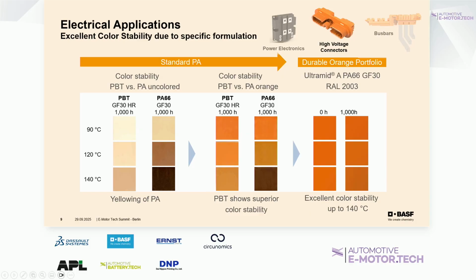And then we said, okay, let's just color it, and maybe the effect is gone, but unfortunately this was not the case. So also if you take an orange pre-colored material and age it with temperature, it still will be brown after time. So what we did, we started the development to decrease this effect as well as possible, and the result is shown here on the right side. You still see a kind of effect, so it's getting a little bit into brown, but it will still be orange after aging, to make sure that you can identify your application, as I said, in case of an accident. So you see, very close together in the e-engine, two applications with completely different requirements.